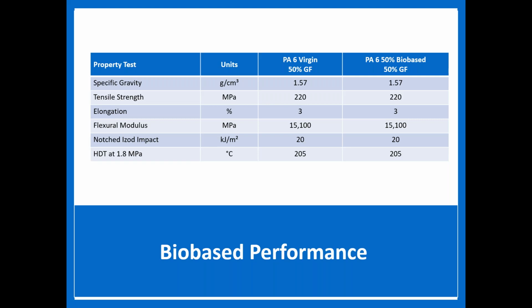So something like a PA6, so your nylon 6s, bio-based versus non-bio-based, you actually see if you look through the whole chart that it is exactly the same, because all we simply did was change out carbons. And so you're comparing it and it's the exact same. So same performance, you're not really giving up much. This would be one of those ones where it may or may not be less money, but your performance will not be affected by it. You would just get the green aspect of it, which is nice.